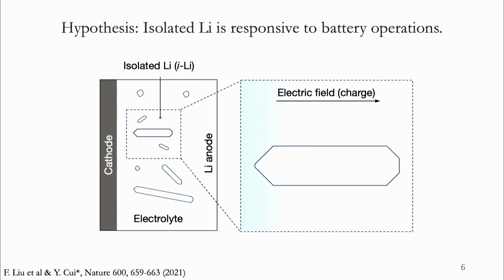We have the cathode and the anode. We have some isolated lithium that formed during the previous charging and discharging process. It's embedded either within the solid electrolyte interphase or in the electrolyte. So during the charging process, we have an electric field pointing from the cathode to the anode. But lithium is an electron conductor, a very good one. So it will be polarized by this electric field, generating surface charges on both of its surfaces.